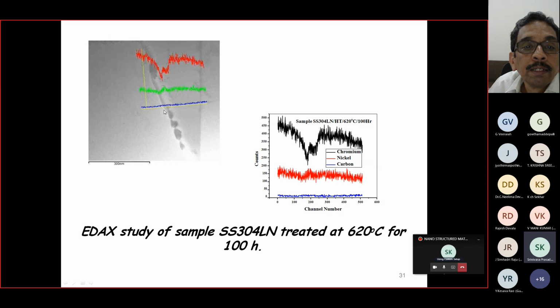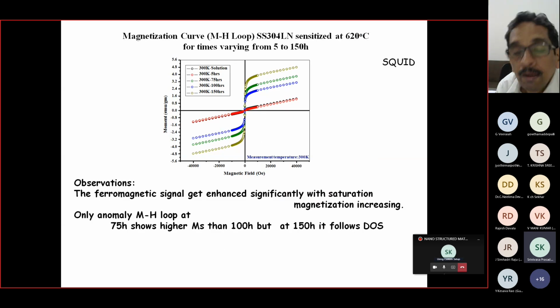Depleted in the sense that here it has, see in this has to come like this. This is the dark region. The chromium is very sort of low in the areas like these things, and here iron and nickel have increased. So that is what I am trying to confirm through my compositional analysis also, that there is a chromium depletion around these particular precipitates. That means chromium has been drawn out of the matrix, and what remains was iron and nickel, which is giving us the ferromagnetic state. Now, I have given enough of evidence to show that the particle is having nanometers.